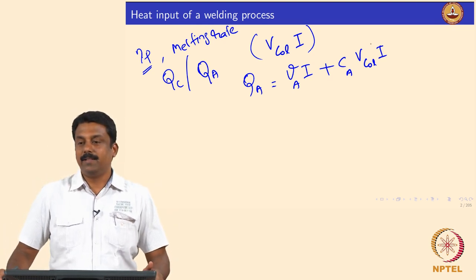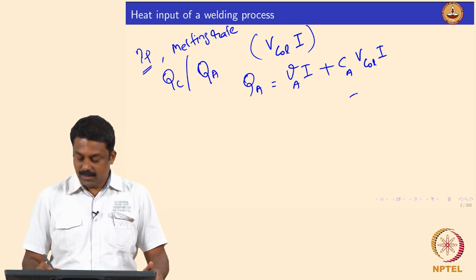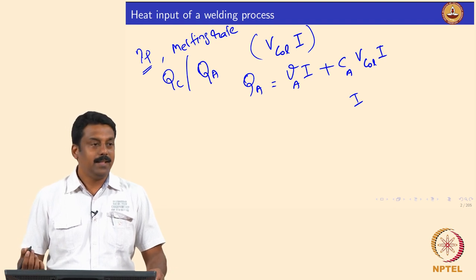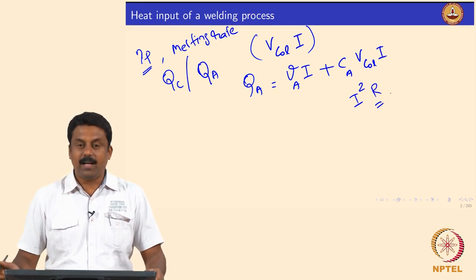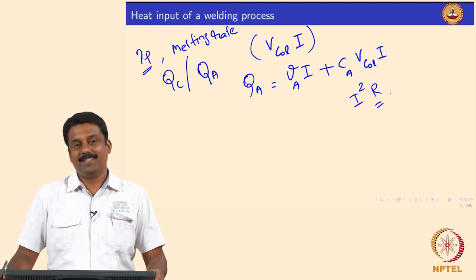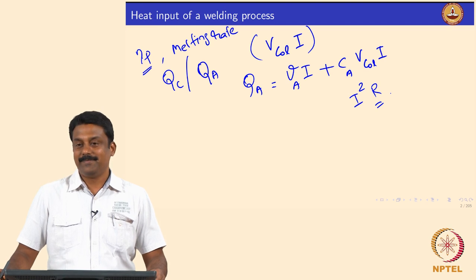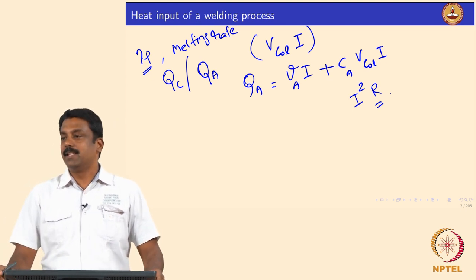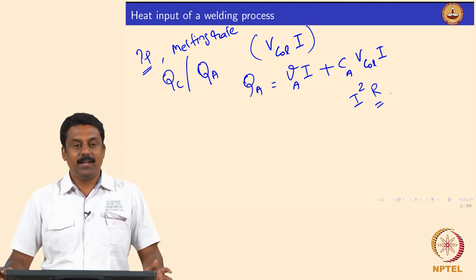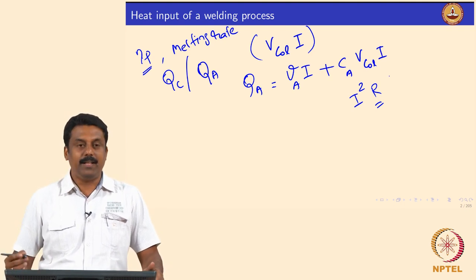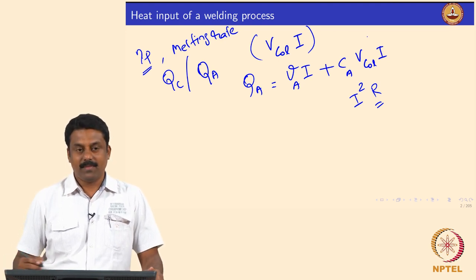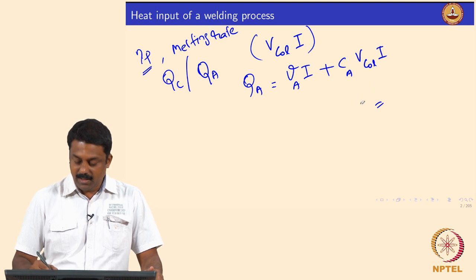V_column times I can be transformed into I times V, which equals IR, and then it becomes I²R. To calculate R, we use the electrical resistivity of the arc — we derived an equation for that. So we derived an equation to calculate the electrical resistivity of the arc so that we can calculate the heat generation in the arc column. That is why we derived that equation.